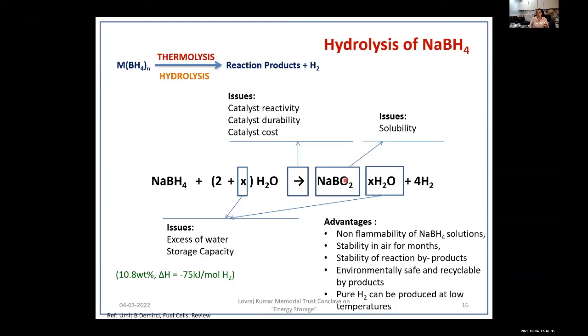But the problem that remains is that a catalyst is required for this reaction, because this is a spontaneous process. You have to slow it down. Sometimes the reactions are very fast, and you have to slow them down because you do not want all the hydrogen to be released instantaneously. So you have to change the pH of the reaction, and then you need a catalyst to get it at the desired rate. Excess amount of hydrogen and the solubility of the compound which you are getting are the other bottlenecks.